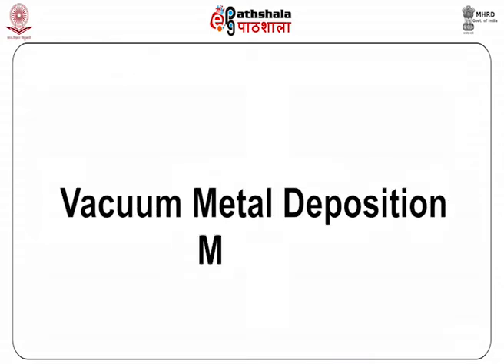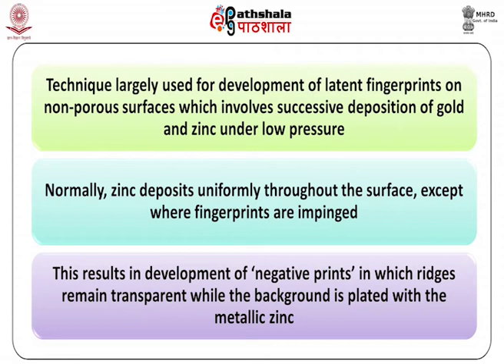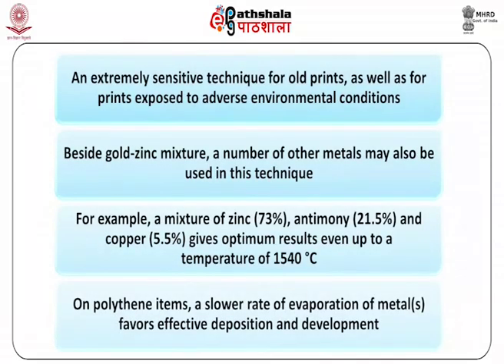Then comes the vacuum metal deposition method. Vacuum metal deposition, a technique largely used for development of latent fingerprints on non-porous surfaces like plastics and polythene, involves successive deposition of gold and zinc under low pressure. Normally, zinc deposits uniformly throughout the surface except where fingerprints are impinged. This results in development of negative prints in which ridges remain transparent while the background is plated with the metallic zinc.